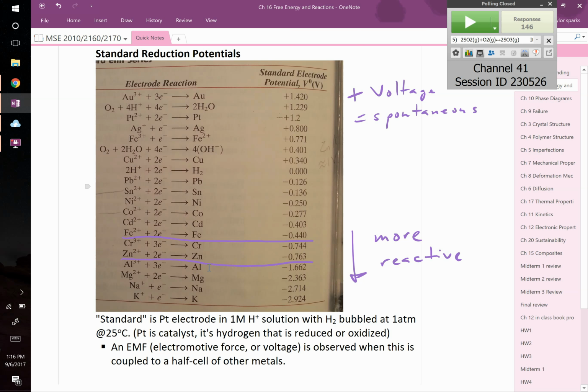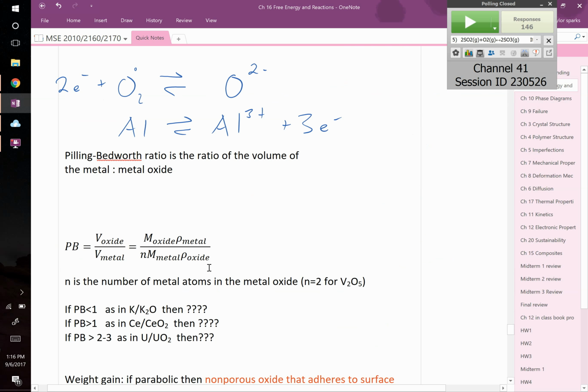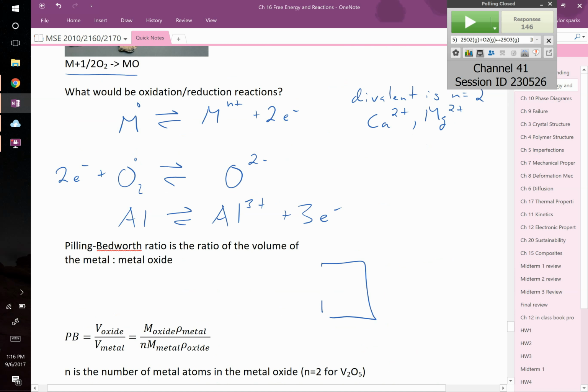And the reason you stop the reaction is because imagine this scenario. You've got your block of metal, and it's going to form an oxide layer on the surface. Here's your MO, metal oxide. In order for this to keep on oxidizing, for that layer of rust, in iron we call it rust, here it would be aluminum oxide, what sometimes they'll call the scale, in order for that scale to keep on growing, you have to have one of two things happen. You either have to have oxygen ions, O2-, go in through that scale, or you have to have metal ions, M n+ ions, traveling through the oxide outwards to the surface.